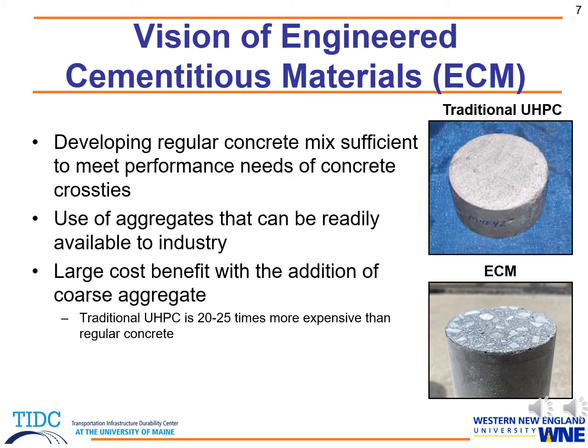So given some constraints that are needed in order to achieve a durable concrete cross tie, we were able to generate a vision of our engineered cementitious material, also known as ECM. So we wanted to generate a regular concrete mix that would be sufficient to meet those performance needs in concrete cross ties. Also, to use aggregates that are readily available to industry. And we also want to include coarse aggregates in our concrete mix. This is a large cost benefit due to the fact that traditional UHPC is 20 to 25 times more expensive than regular concrete.